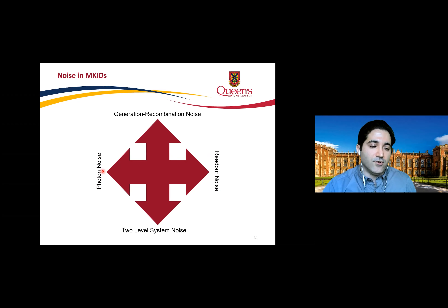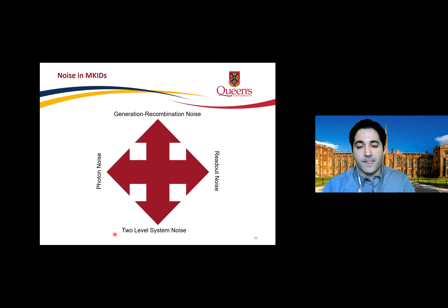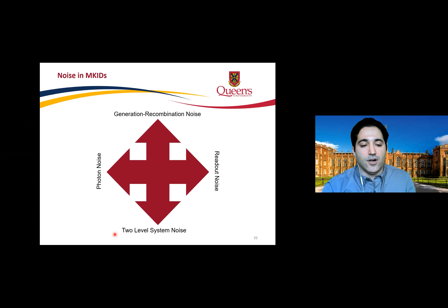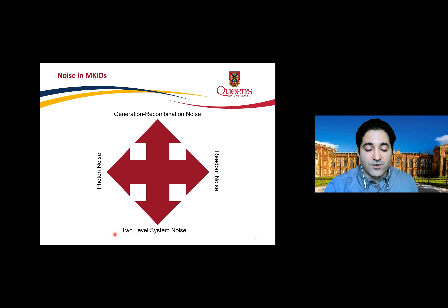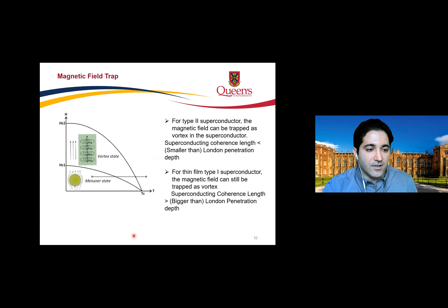There is also photon noise intrinsically associated with the Bose-Einstein arrival rate of photons. Another noise source is two-level system (TLS) noise, which comes from the interface between metals — for example, oxidized surfaces or multiple metal layers deposited on top of each other — creating a small amount of phase noise. We do not yet have a very precise model for TLS noise, but researchers are working to explain it physically and eliminate it to achieve a higher signal-to-noise ratio.